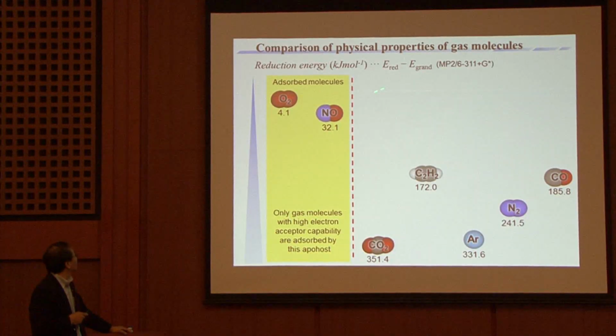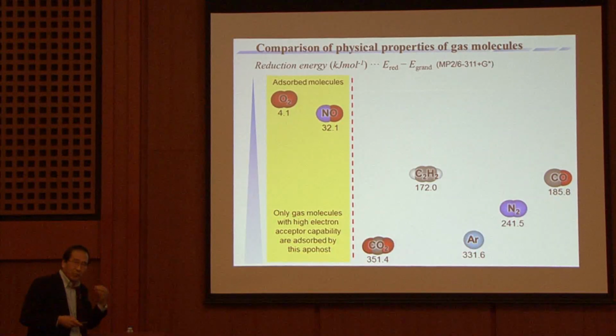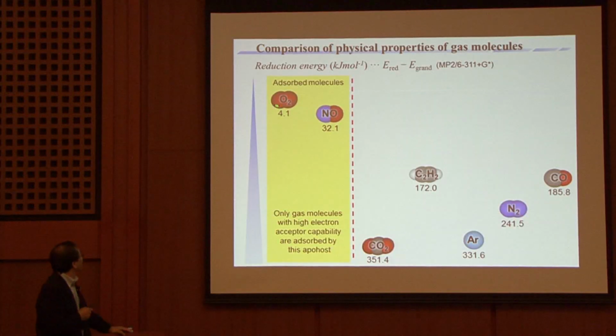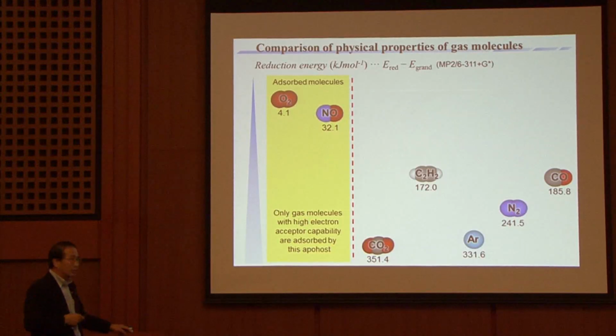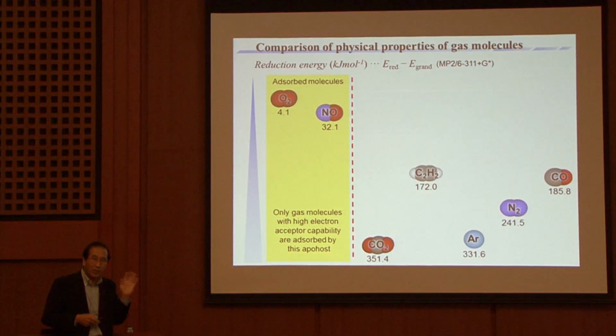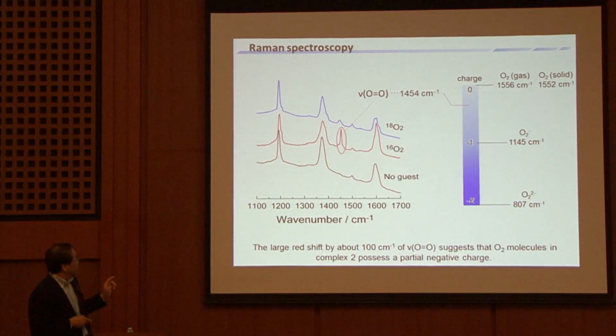But anyway, this is the capacity of the molecule to be reduced. So only O2 and NO have a lower value in this case, because of the unoccupied orbital. Then we observed the Raman spectroscopy in situ, and the value is 1454 wave number, in between the neutral oxygen and the superoxide type.